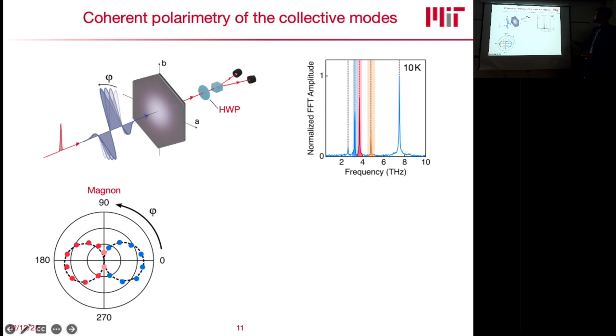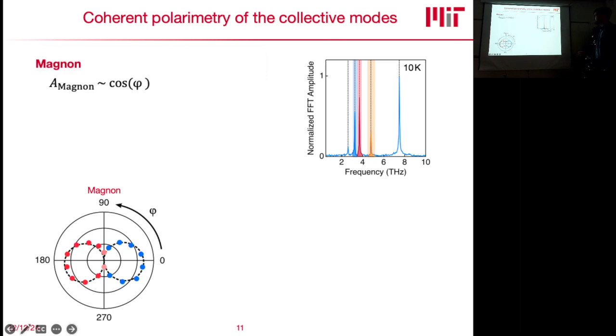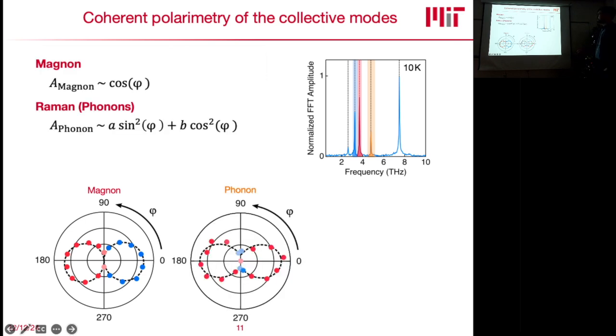And we can go one step further, and we can now analyze the symmetry of these modes. So we can do so-called coherent polarimetry of these collective modes by rotating the angle of our terahertz excitation with respect to the crystalline axis. So this is this angle phi here, which is then shown in this polar plot down here. So for the magnon, you get something that looks like a dipolar pattern, as we would kind of expect because we're linearly exciting it. And so it should follow a cosine behavior. For the Raman, since it scales with E squared, we would expect the square of this dipolar pattern, which is exactly what we find. So here, both lobes in this direction have the same sign, whereas here it's positive and it's negative.